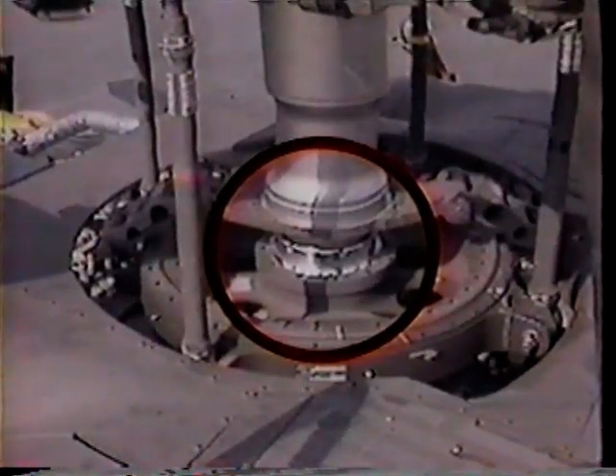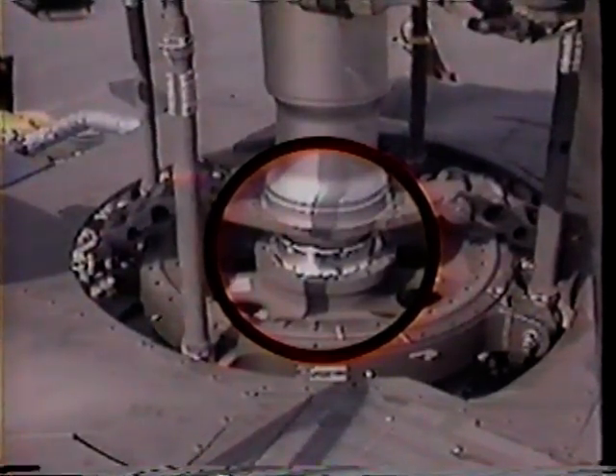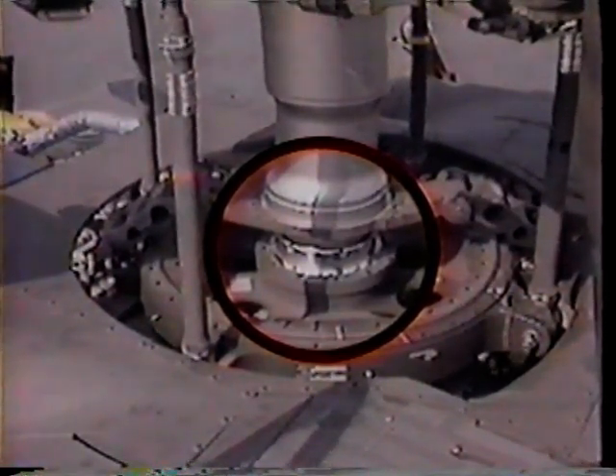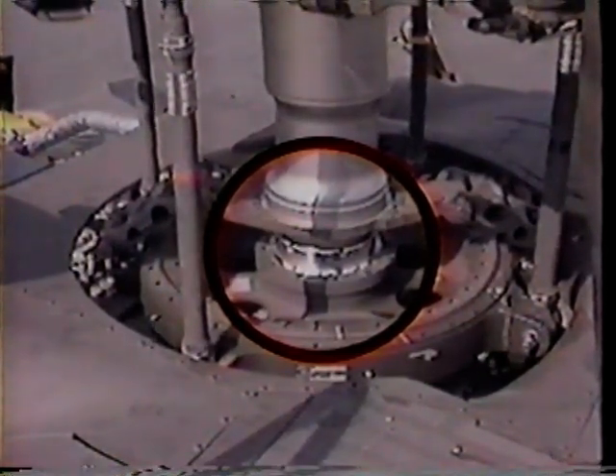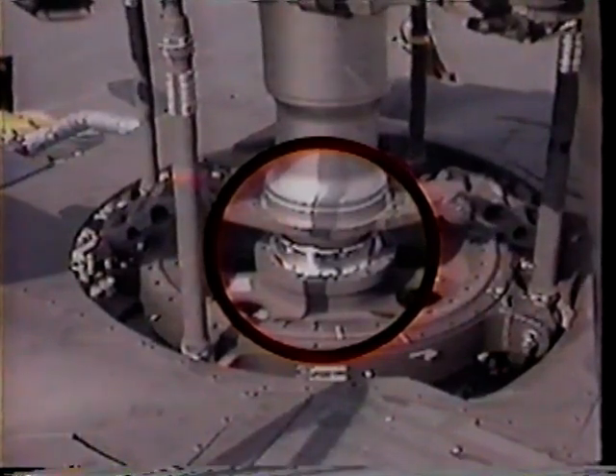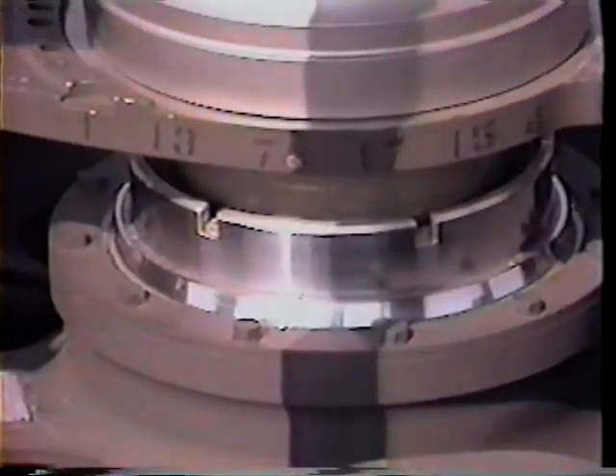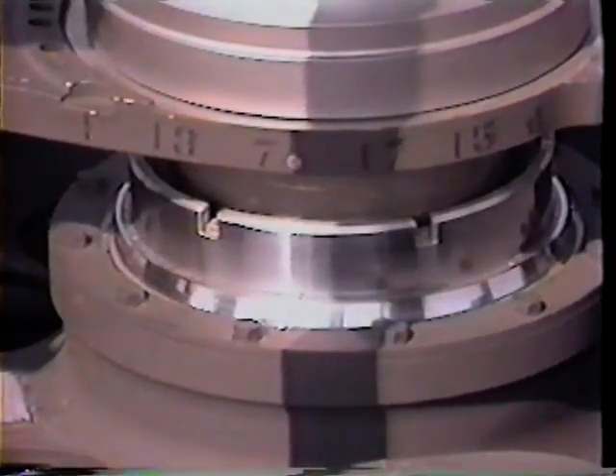The uniball is next. It's the bearing portion of the swash plate assembly located at the base of the main rotor shaft. It allows the fixed swash plate to tilt about the rotor shaft. Uniball components are made of aluminum and plated with chrome. Sometimes moisture gets under the chrome plating through a pit. This enables the galvanic effect to corrode the aluminum. When the aluminum corrodes, it causes the chrome plating to blister, crack, and flake off.